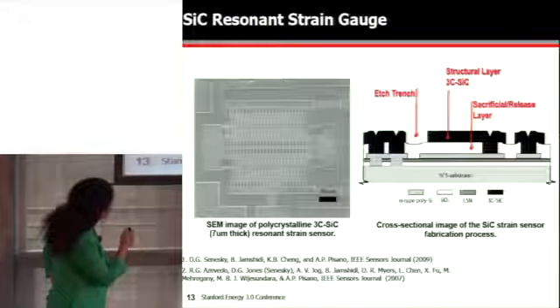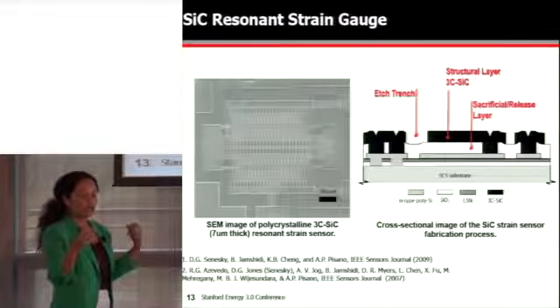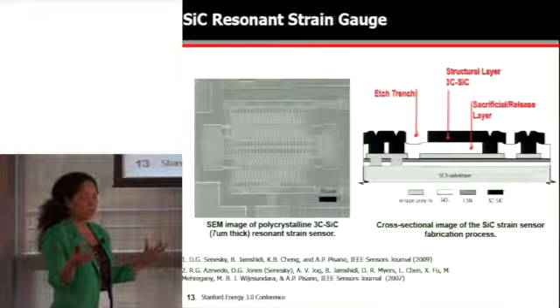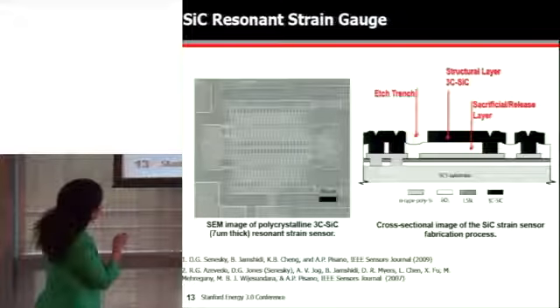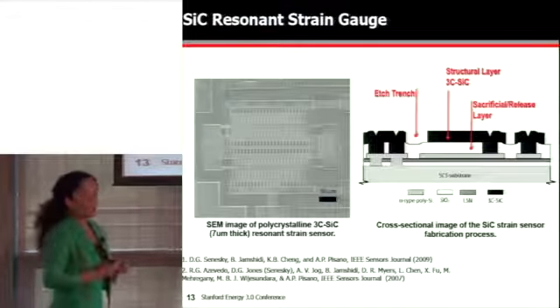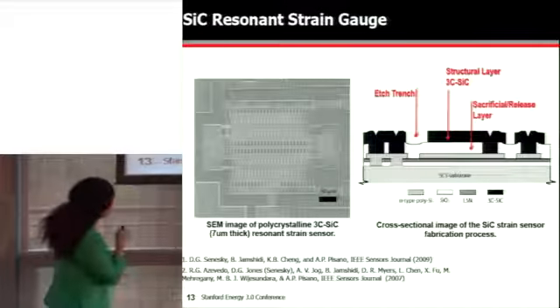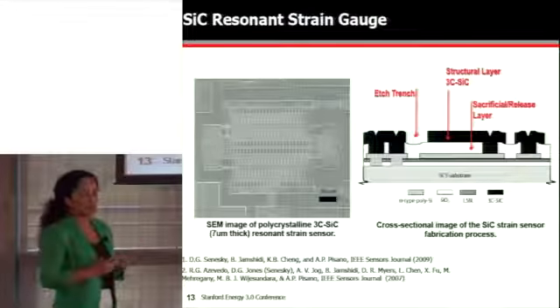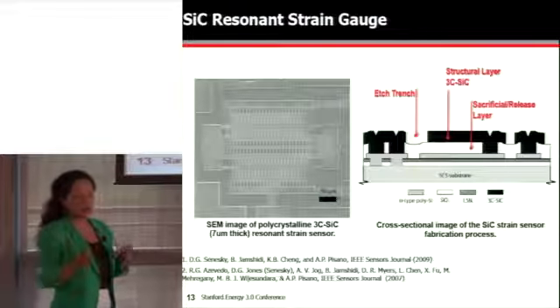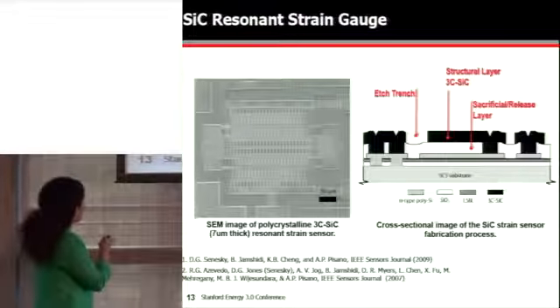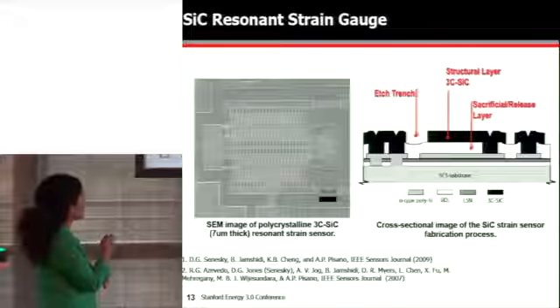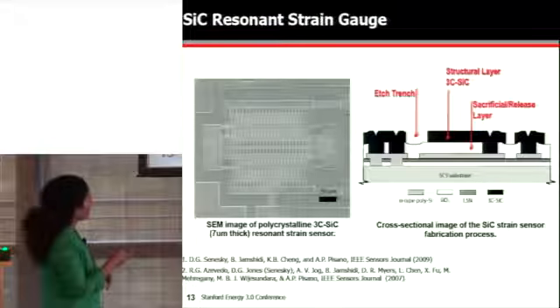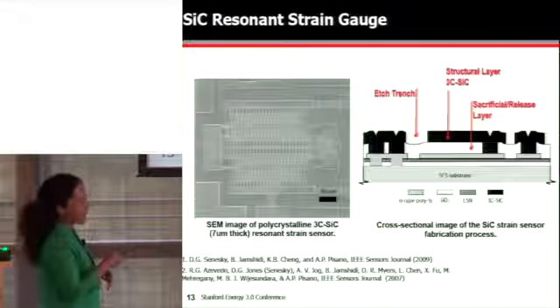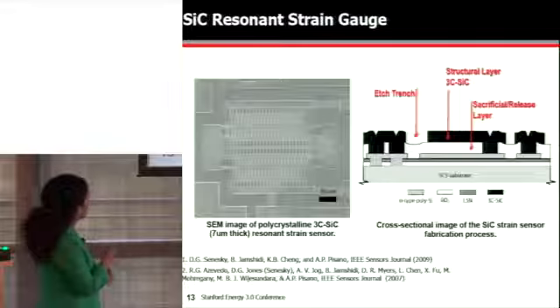You have these tines here that as you stretch the tines, you get a change in the natural frequency of the structure, and you can actually induce vibration within these tines using these interdigitated comb fingers. And as you apply strain to these tines here, the resonant frequency will shift. It'll shift due to the applied strain. So this is a microscale strain sensor made from silicon carbide. And we do that by using microfabrication processes to pattern the silicon carbide and also release the underlying substrate. So this is a freestanding structure here.